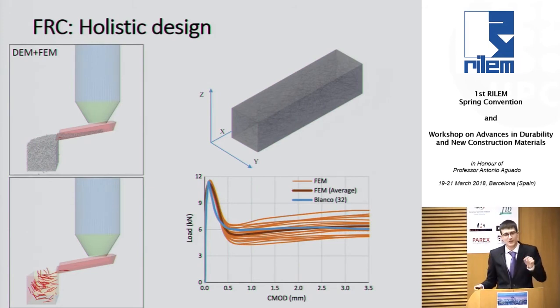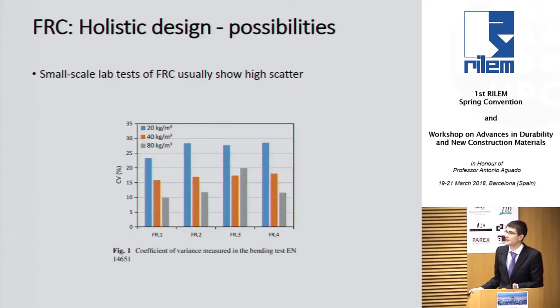And it's interesting because every time you run the simulation, since the fiber distribution is different, you have a different curve, because the fibers are not located exactly at the same position. So the holistic vision is giving us a possibility of measuring the variability of the material, even the scatter it might have. And you know that you have high scatter in fiber-reinforced concrete. It varies depending on the size of the element. It varies depending on the fiber content.